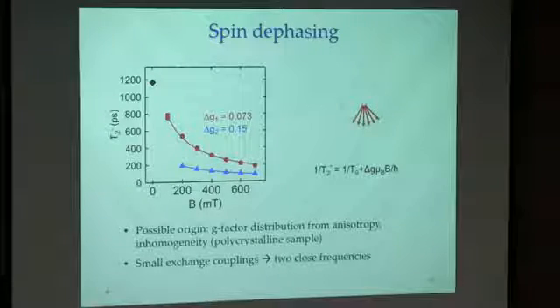Yes. So normally we would think of that as being the T2, the intrinsic T2. So I'm a little confused as to the difference between that term and T0. Here I would say that it's dominated by spin dephasing because of the G factor distribution. But the true spin decoherence time would be when you have only one G factor, so you have only one spin, and how fast it loses its phase. That would be the true spin decoherence time. But at least we can infer that the spin decoherence time is also long, at least longer than this time. And what I just described as exciton states, we have really two pairs of very close frequencies.